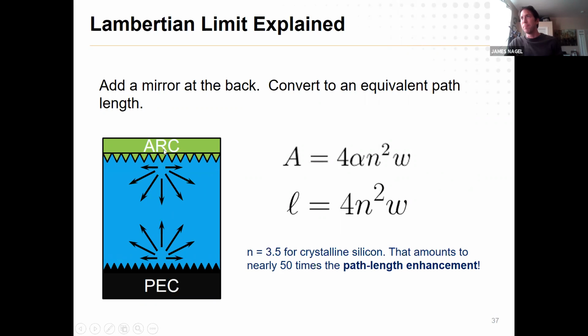So initially we had an ARC at top and another at the bottom. So what if I just make it a mirror at the bottom here and I keep scattering with each reflection? So that adds a factor of 2. And then we apply that natural log term from several slides back. And so when all of the dust settles mathematically, you eventually find that the total equivalent path length of this thing is 4n squared W. So that same Yablonovitch limit is sometimes also referred to as, quote, the 4n squared limit of path length enhancement.